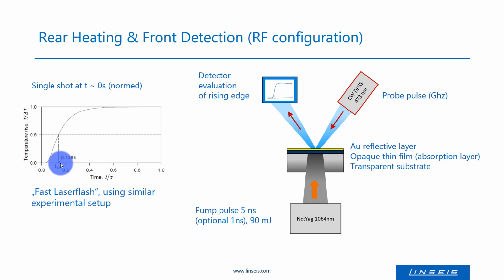Nevertheless, there are two main disadvantages of this configuration for the measurement of thin films. The first one is that we need a translucent substrate, which allows the laser beam of the heating laser to pass through and only absorb at the back side of the sample. The second one is that even with a nanosecond pulse laser and high-speed data acquisition, thin films must be in the range of hundreds of nanometers to micrometers for a measurement.